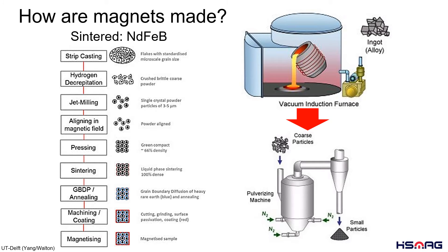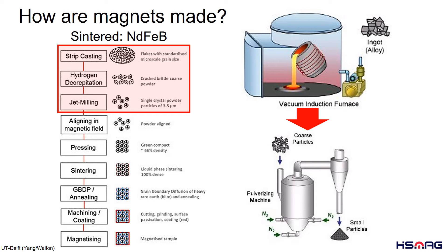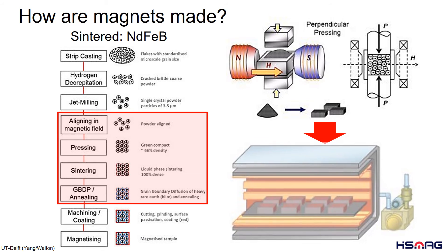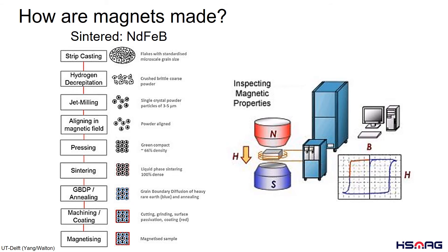So how is a magnet made? Let's look into the sintering process first. The materials are melted in a furnace and cast into ingots, which are then pulverized into particles. These magnetic particles are placed in a jig and subjected to a magnetic field while being pressed into a shape, resulting in anisotropic magnets. The ingots are then heat treated in a sintering furnace, reducing their volume by approximately 50% and doubling their density. After sintering, the magnetic properties are checked.